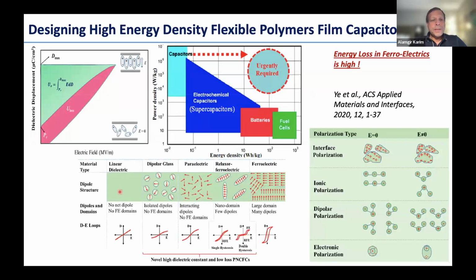So now the choice of materials, okay? As I said, ferroelectrics, as you see, have domains, and the area under the hysteresis of this curve, that's the loss. So you lose energy. So ferroelectrics are high, but the charge-discharge is not favorable. A linear dielectric has no loss. It linearly goes up and down with electric field, the energy displacement vector. So we want these, and maybe it's something in the middle that we can be comfortable with.